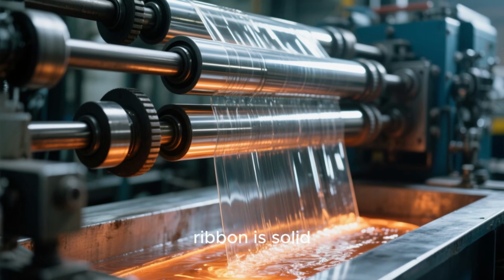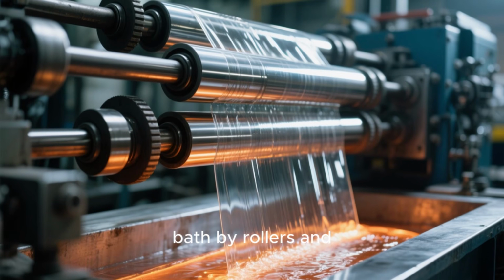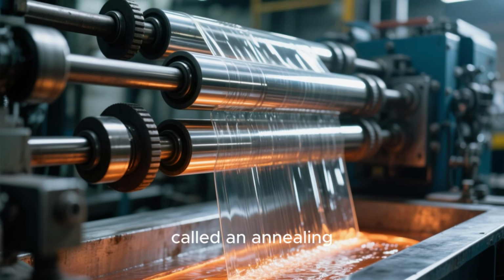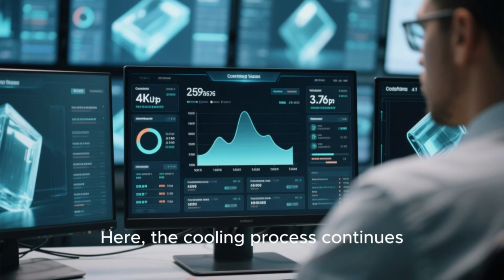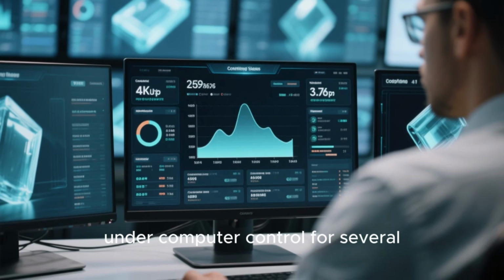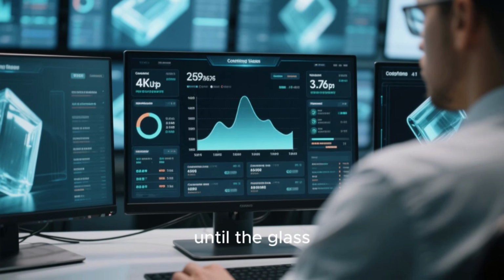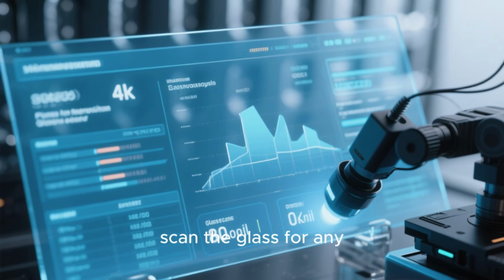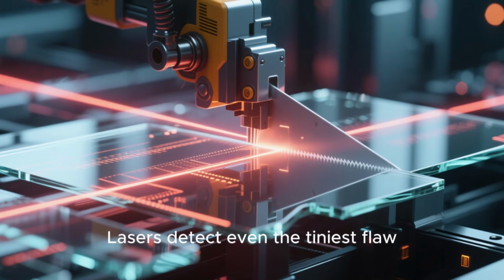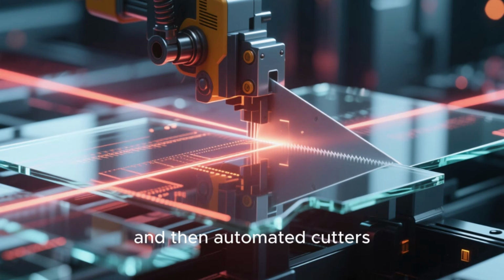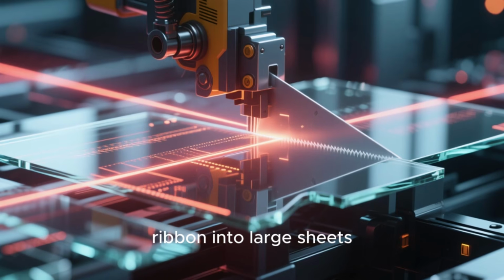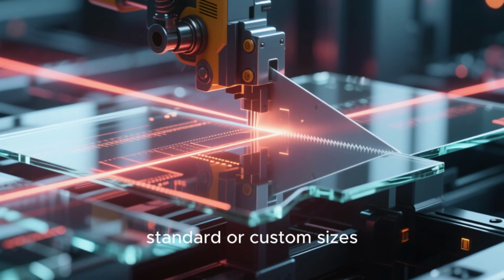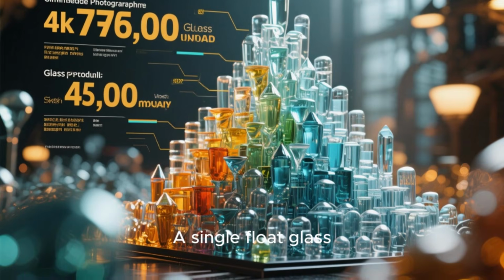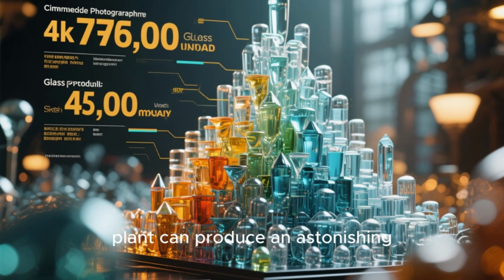Once the glass ribbon is solid enough, it is lifted off the tin bath by rollers and enters a long cooling chamber called an annealing lehr. Here, the cooling process continues under computer control for several hundred meters until the glass reaches room temperature. Finally, at the end of the line, advanced sensors scan the glass for any imperfections. Lasers detect even the tiniest flaw, and then automated cutters slice the continuous ribbon into large sheets, which are then cut to standard or custom sizes, ready for shipping. A single float glass plant can produce an astonishing 6,000 kilometers of glass per year.